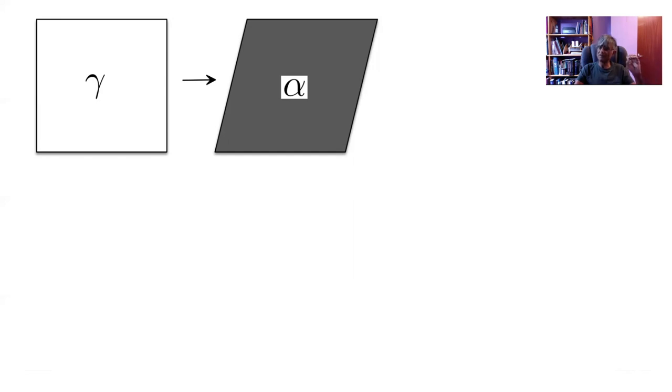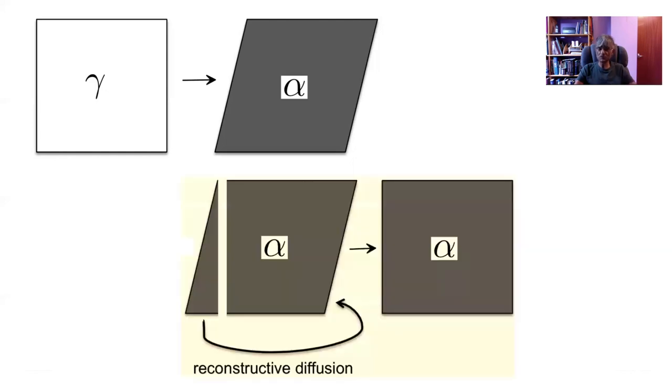So you can get martensitic transformation in pure iron by cooling at a sufficiently large rate. That would lead to a shape deformation, which looks like that. And when we cool the pure iron slowly, we do not get this shape deformation, but we get the change in crystal structure. So you can imagine that to happen in two steps: you have this displacive transformation, you then cut a triangle off here and you bring it to this point so that the external shape is maintained.